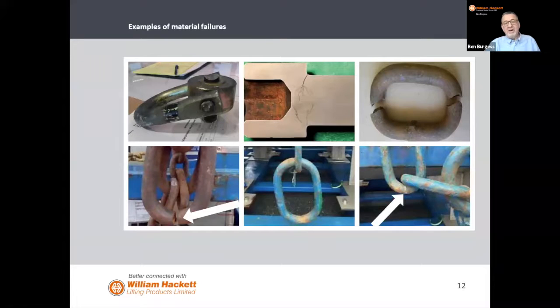What you have here are a number of images of products that have failed due to hydrogen embrittlement. I'm going to pick up on a point that Mark mentioned earlier. The challenge with these issues is that they happen from the inside out. The accumulation of the hydrogen happens within the steel structure. It's not like a surface crack or wear. It happens from the inside out, and it creates the internal pressures that then go and break.